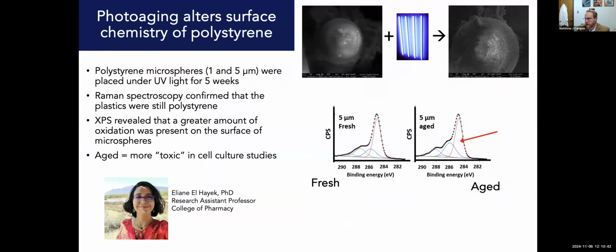Our first real foray into this was asking whether the polystyrene microspheres that are easily available for research purposes would be a viable model for us. So we got these 1 and 5 micrometer polystyrene microspheres, and we thought, well, what would happen if we just aged them under UV light for 5 weeks?